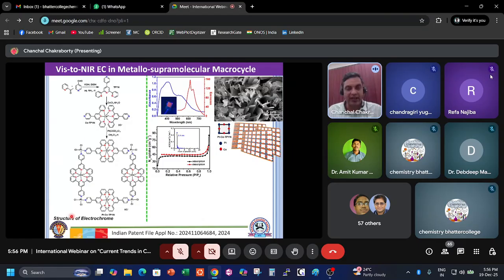So it can give a dinuclear platinum MLCT emission inside, and it can give a red emission, which is very unique for platinum, or even gold or palladium kind of metals. It's a porous structure with a surface area of around 50 meters squared per gram. 2.1 nanometers is the pore size, and that actually matches the molecular pore size of this material.